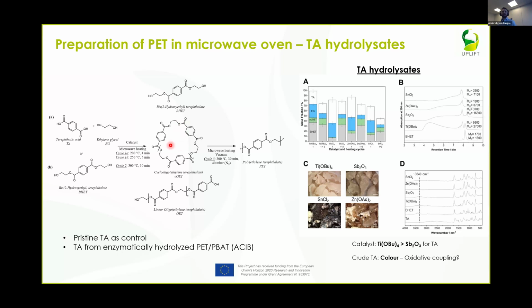If we start with the hydrolysates, so taking the upper part of this diagram first, using that to produce intermediates can be done thermally, but what we have also done here is investigate this through microwave chemistry. Microwave chemistry gives us the ability to screen faster. We don't need to use days to polymerize these systems. We can actually do this within hours, and that therefore permits us to investigate the use of different catalysts so that we can also investigate less harmful types of catalysts.